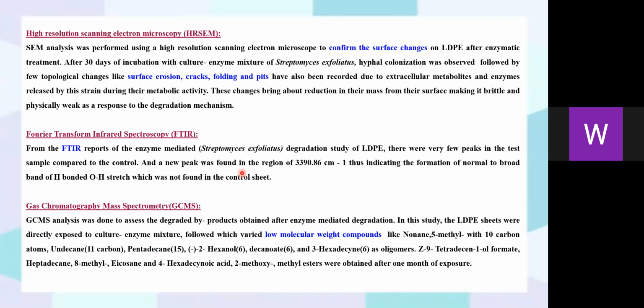SEM was performed using a high-resolution electron microscope to confirm the surface changes after enzymatic treatment of 30 days of incubation with culture enzymes of Streptomyces exfoliatus. Hyphal colonization was observed, followed by a few topological changes like erosion, cracks, folding, and pits due to extracellular metabolites and enzymes released by the strain during their metabolic activity. These changes bring about reduction in mass from the surface, making it brittle and physically weak as a response